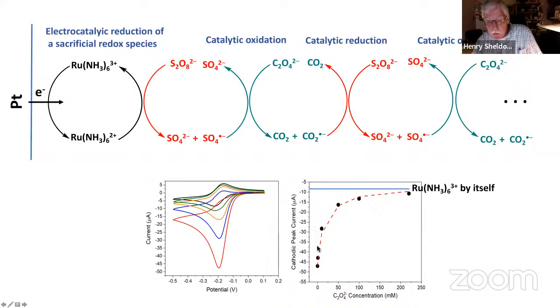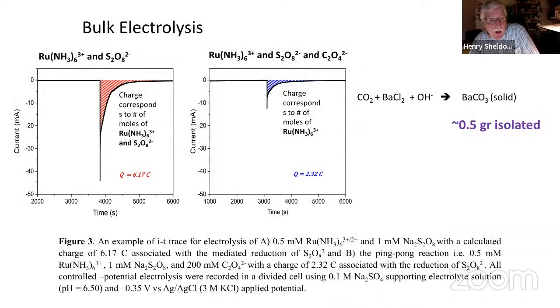This is a plot of the peak current versus the concentration of oxalate. And so this is when you have persulfate in the solution. That's the electrocatalytic current. And then you start adding oxalate, and that current goes back to the peak current for the reversible reduction of ruthenium hexamine. All right. So that's one bit of evidence that this is all working.